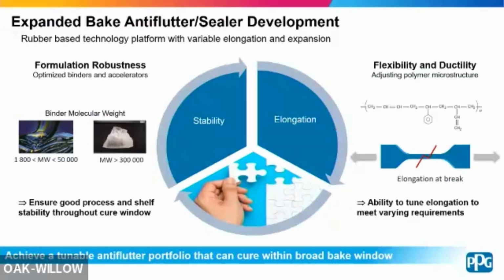On the stability side, so we have to enable that low temperature cure, right? So thinking about tuning that accelerator package like I mentioned before, while maintaining that shelf stability. You also need to think about process stability, so that formulation robustness. We really need to optimize the binders as well to make sure we get good process stability throughout that cure window, and then over time as well. And that just comes down to, in a lot of ways, binder molecular weight. So can we tune different binder molecular weights to achieve that kind of stability that we need?